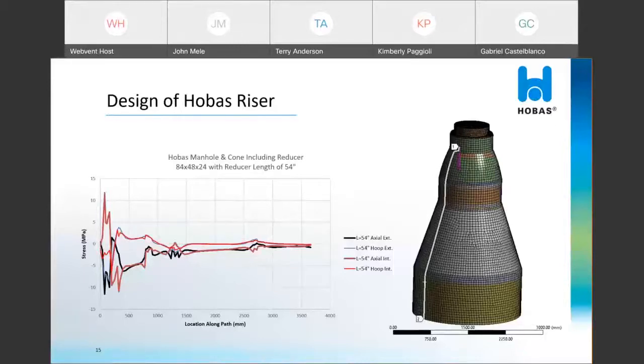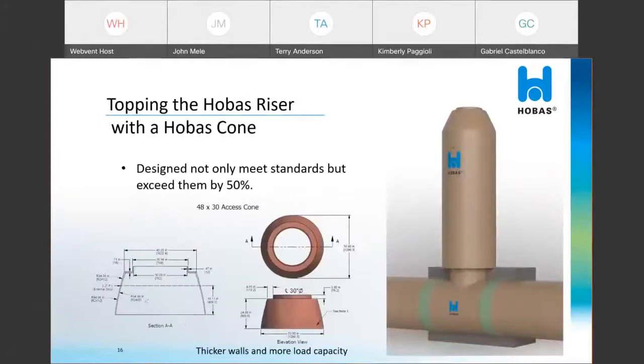First, that the manhole met the required loading conditions per ASTM D3753. Second, that the manhole's cone was so strong that the concrete rings broke well before there was any damage to the cone itself. Third, the strengths measured were very consistent with what we found in the FEA, proving our model worked. The Hobas riser pipes will then connect to our new Hobas cones. The cones have been designed to not only meet the required ASTM standards, but exceed them by a minimum of 50%. I will now turn it back over to Kim to discuss testing.